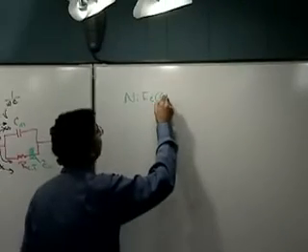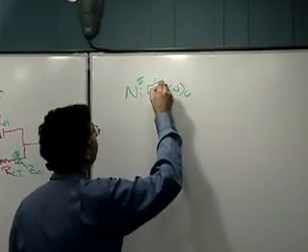That gave us this time dependence to the diffusion coefficient. So the question is, yes, there's a time dependence to the diffusion coefficient, but is the physical meaning that I have given you for that correct? That it's actually the lattice parameter changing that's giving this time dependence. And so we went back and said, well, if that's the case, let's go to a potential where a small perturbation will not dramatically change the number of ions in the layer, and hence will not dramatically change the structure of the layer. And let's see then what happens in terms of the diffusion coefficient. Because if our model's right, then suddenly we won't have a time-dependent diffusion coefficient anymore under these circumstances. So we pick a potential based on the cyclic voltammogram for nickel ferricyanide, which you will recall, where we're perturbing the 2,3 oxidation state of the iron.